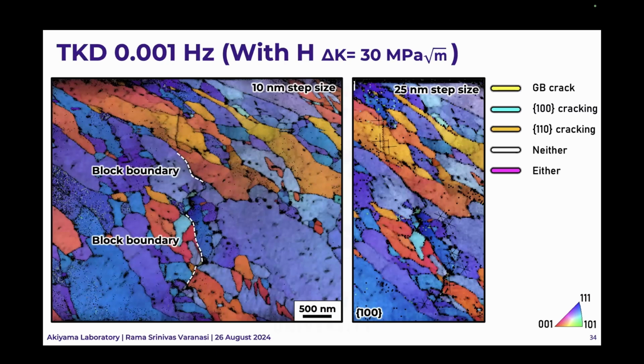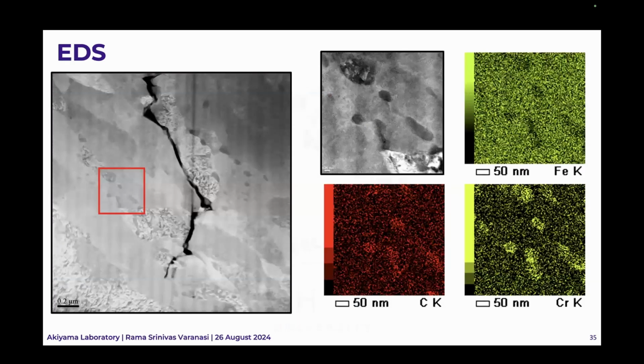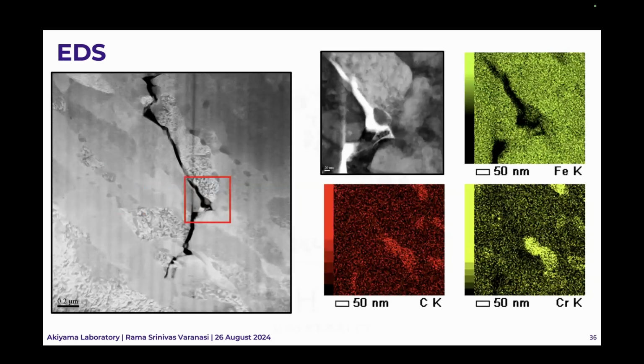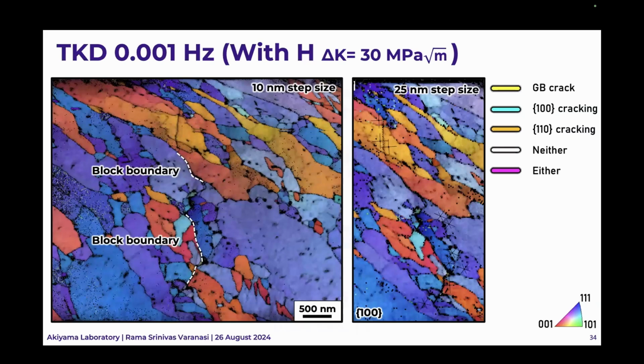Here we have this crack which is propagating along the block boundaries. There's this very interesting feature here, which is transgranular crack propagation. And we also see these are trans-lath cracks where we cannot exactly determine with TKD whether this is 100 or 110, because it could be either of these based on the trace analysis. Now, when we look at EDS, we have these chromium-rich carbides. And this is the area I was talking about a couple of slides ago, which is an area where there are block boundaries, but this intersection is actually a trans-lath crack.